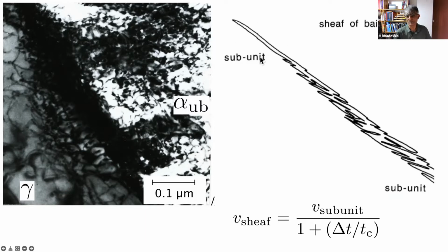And this problem has been treated quantitatively. And the important thing to note is that the velocity of growth that you measure on an optical scale will be much smaller than the velocity of growth of individual platelets, because there's a time period involved before a subsequent platelet forms. Right, so is there a high-resolution technique in which we can observe the growth of individual subunits?